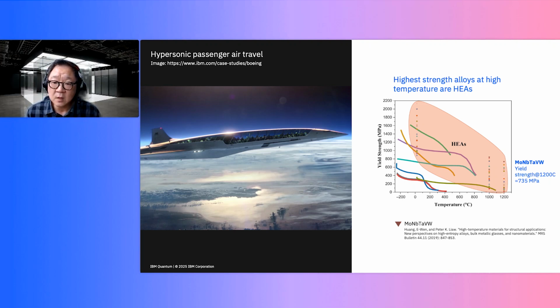Now, one of the challenges with hypersonic aircraft is that the leading edges, the nose, and the front edges of the wings can get very hot. 2,000 degrees Kelvin is not unusual. And what happens at those temperatures is that structural materials start to soften. They get hot, they melt, or they start to soften like butter will do when it's warm. The chart you see on the right is yield strength on the y-axis and temperature on the x-axis. And these lines that you see in different colors are different structural metals typically used in airframes.